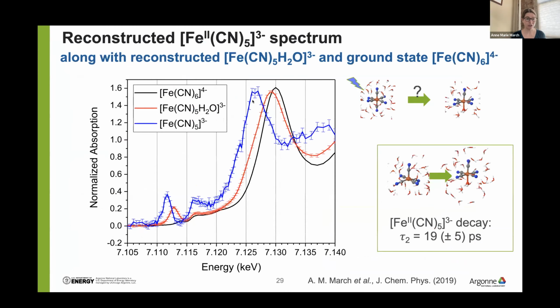And so, long story short, we went ahead, we measured a whole bunch of XANES at different delays, a whole bunch of kinetic scans at different energies, did principal component analysis, global fitting, and with all of that, we were able to, in fact, pull out the signature of the pentacoordinated species and reconstruct its spectrum. So that's what's shown in blue here. And so we could show that, so you absorb light, you create this pentacoordinated species, it decays with a time scale of 19 picoseconds, and then a water comes in to bind.